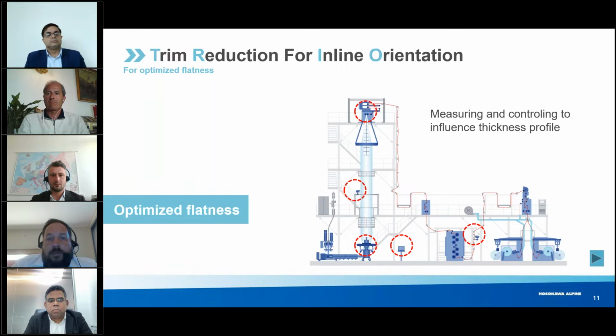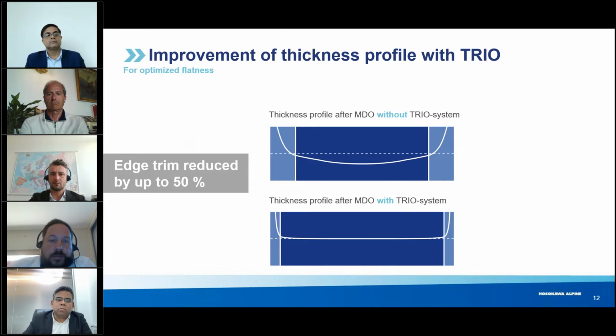This means the film bubble is made a little bit thinner in these artificial areas. That helps to prevent the buildup, because there's less material in this area, and the buildup will still happen, but will be compensated because of the thinner areas. This is how a typical MDO film profile would look without the trio system. It's like a banana-shaped profile, and you can see this is what the build-up will produce here at the edges. This will lead to a very, very big trim wastage.